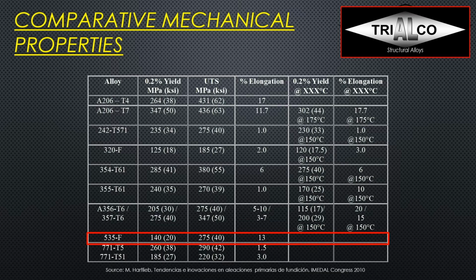Well, the 535, if we compare it, has an interesting property package because this is an F, as-cast condition. I'm actually reaching 20 KSI, 140 megapascal yield strength, but I reach the same tensile strength as we had in A356 T6, and I have higher elongation. So 13% elongation, and that's not unusual for this type of alloy. So very interesting property package.